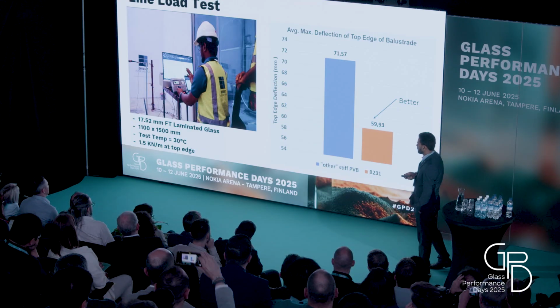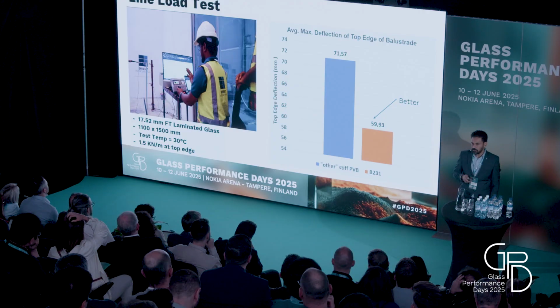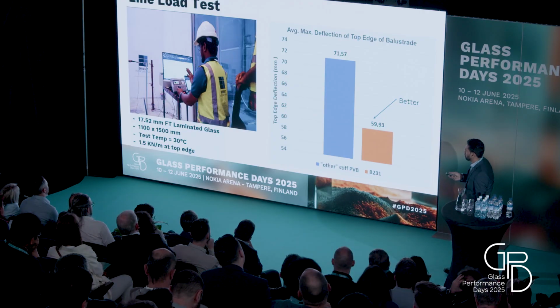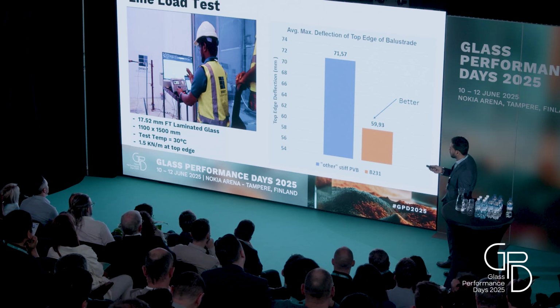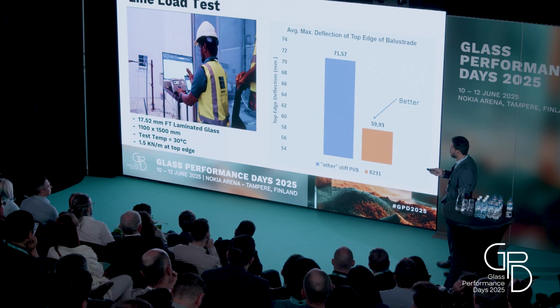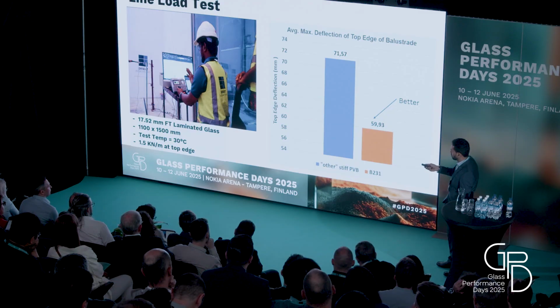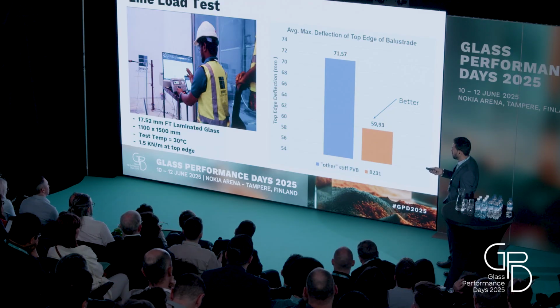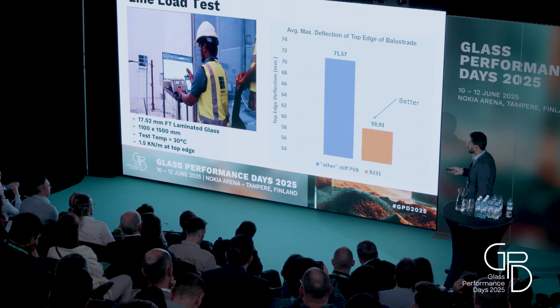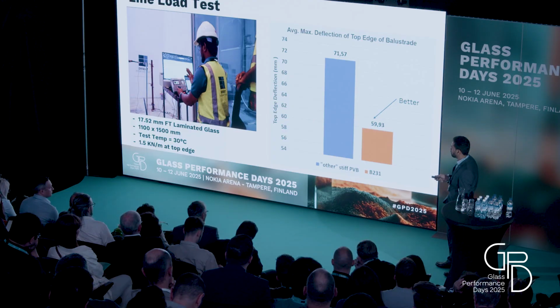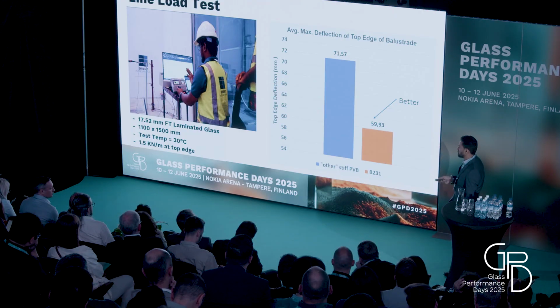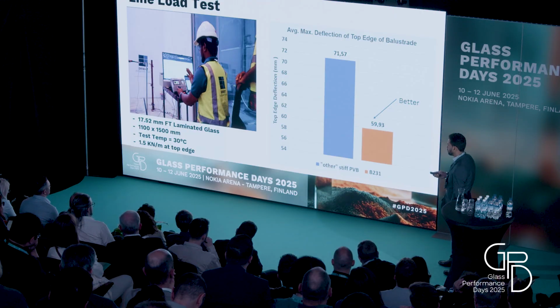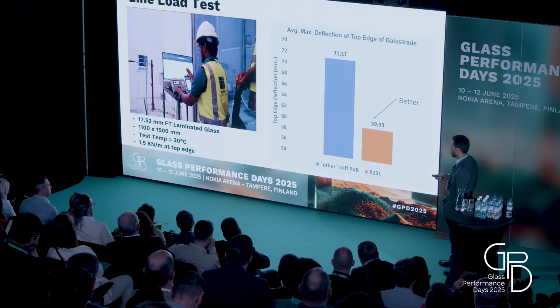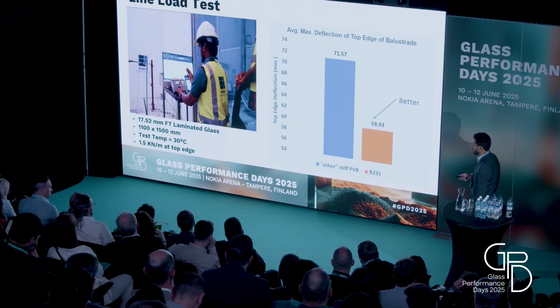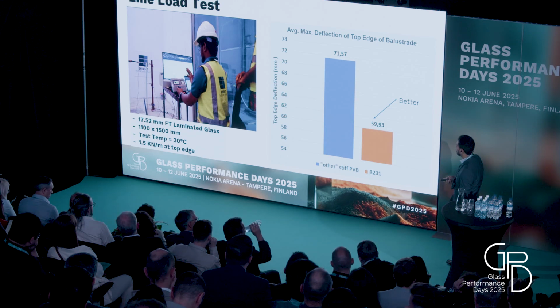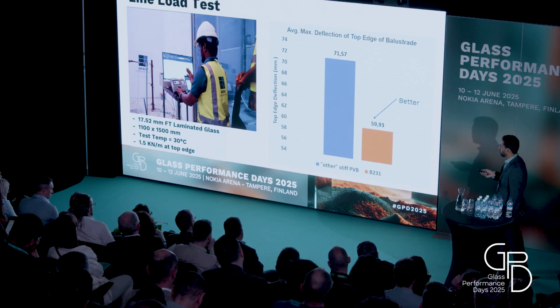We wanted to test the structural performance and the creep behavior in a real application, which could be a glass balustrade. So here we conducted the balustrade test, in the photograph. You can see there is a glass balustrade which is supported only at the bottom edge, and it is being subjected to a line load at the top. Again, the same construction that we analyzed in MEPLA. It is 17.52 mm FT laminated, 1.1 is the standard height of the balustrade, and subjected to 1.5 kN per meter load. And here we have a comparison of the deflections.